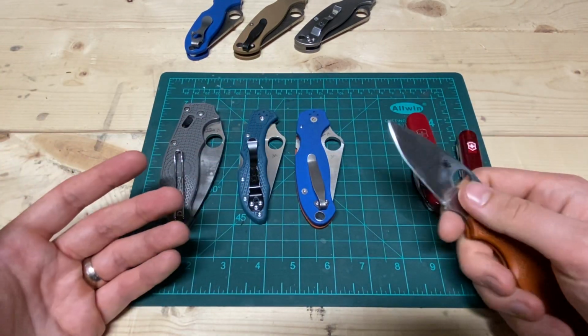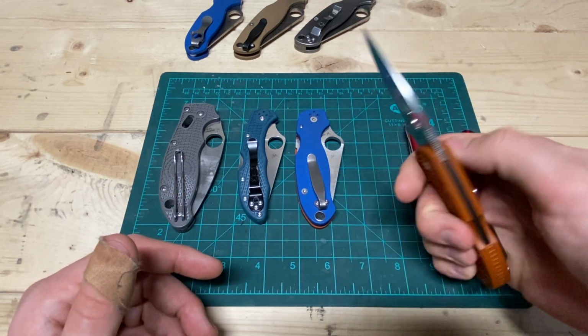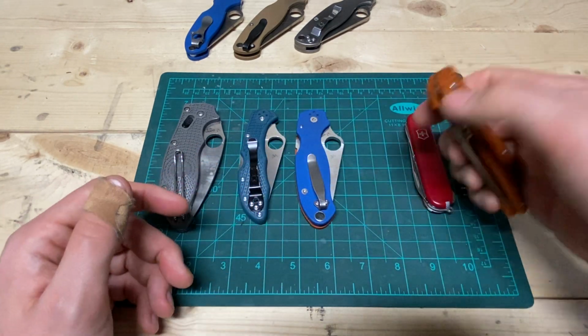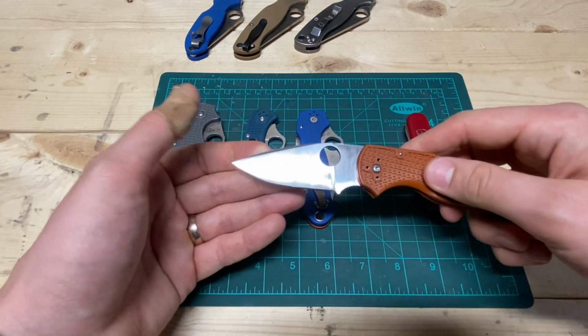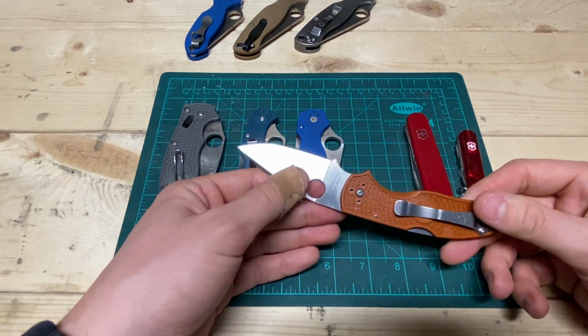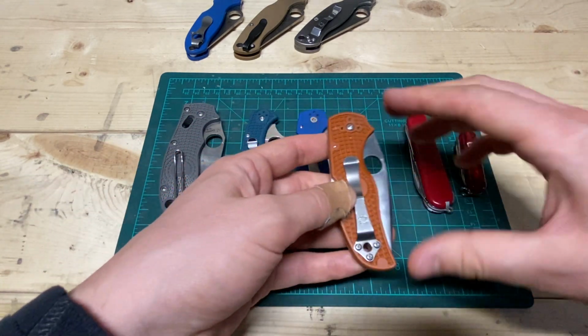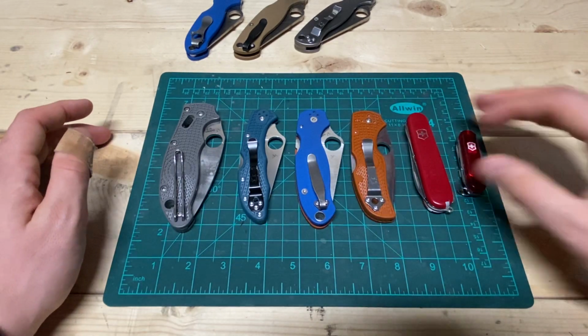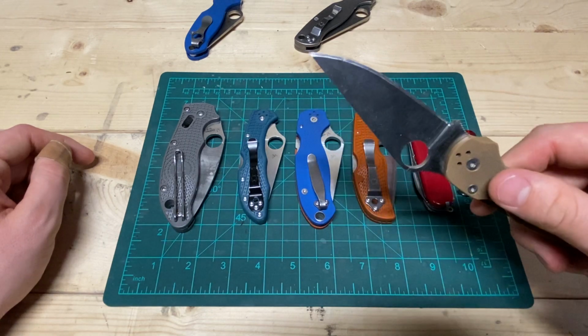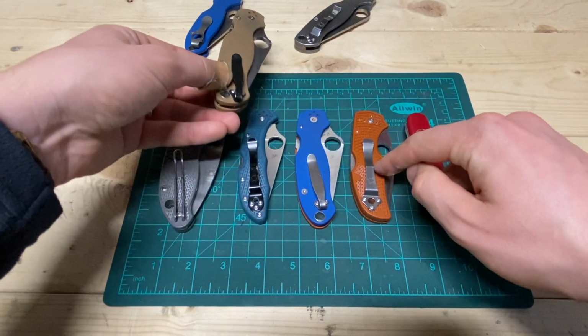That was something totally new for me, and I noticed it especially in this Native here. I've put this to some hard work. It was a whole new level. And after experiencing that, it really satisfied my urges for different work steels, because it was just doing what I was really asking a steel to do in a work environment. As a point of comparison, here's 10V that I used in that same environment. Same edge angle at 15 degrees per side, it rolled, whereas this did not.